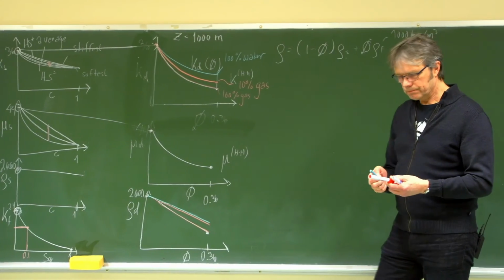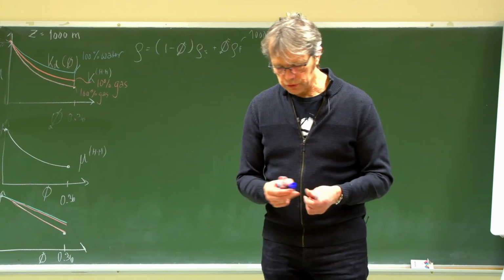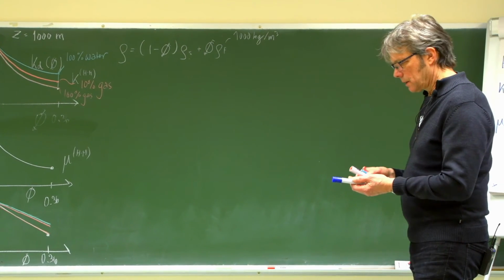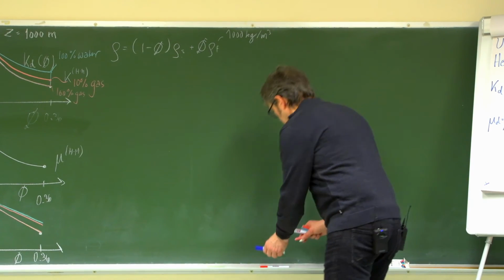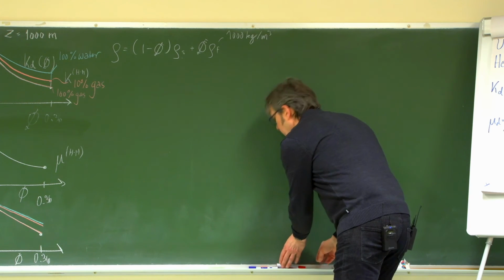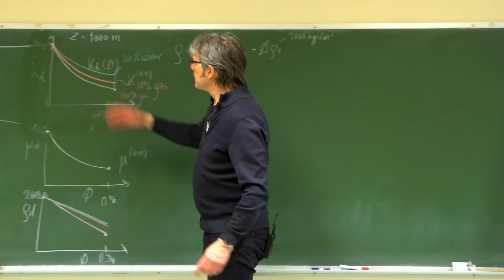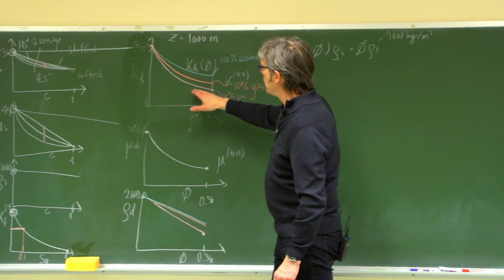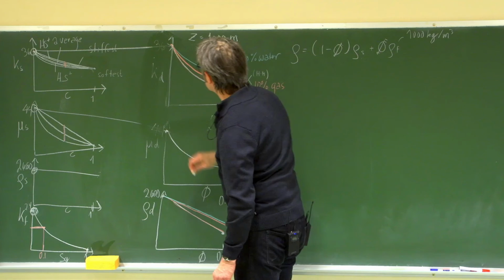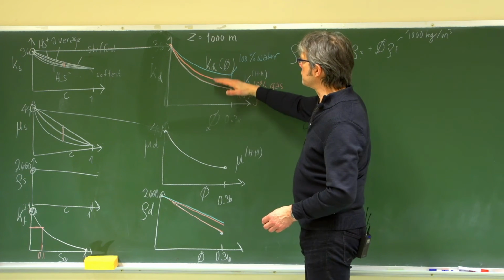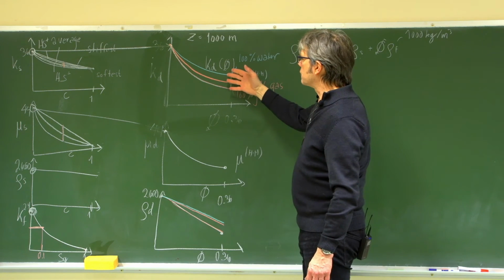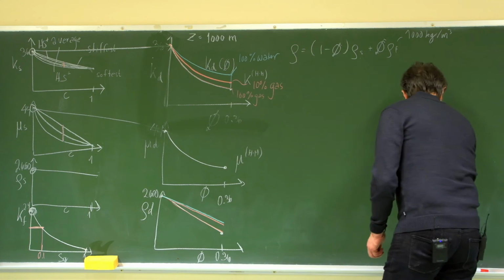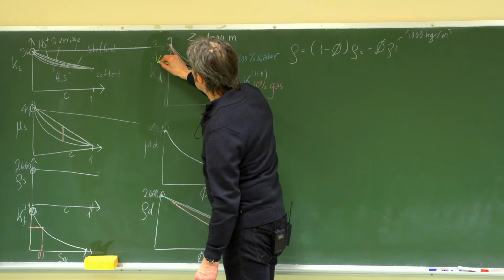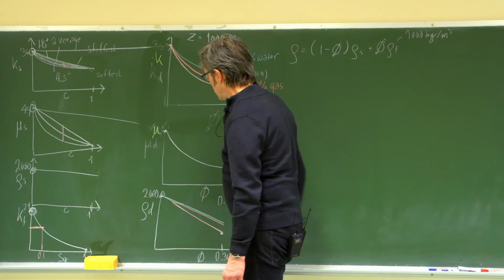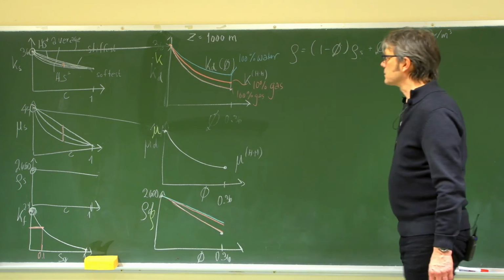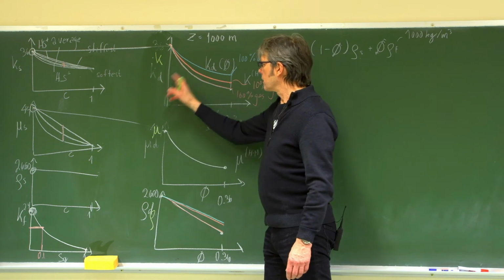Okay, so we have reached quite far now, because now we more or less have all the values we need to make the final template. I would say that the K dry is only associated with the white line here. Now the curves with the colors here are a dry rock that's filled with some fluid. So the green here means the bulk modulus and shear and density with the fluid inside. So for the colored curves, it's the total bulk modulus. The white one is the dry modulus.